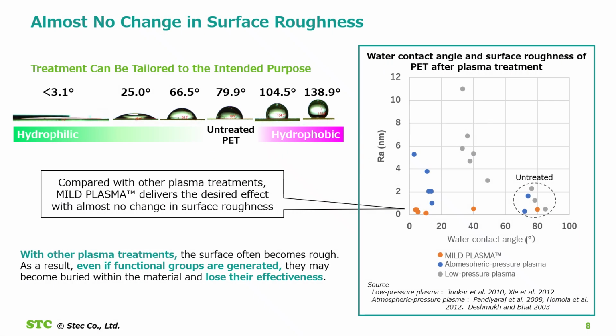Second, it causes almost no change in surface roughness. This is another major differentiator. Many conventional plasma treatments improve wettability, but they also roughen the surface. That can be a problem, especially when smoothness is critical. Take a look at the picture on the right. It shows water contact angle and surface roughness of PET after plasma treatment. It indicates that compared with other plasma treatments, mild plasma can minimize the surface roughness. In fact, with other plasma treatments, the surface often becomes rough. As a result, even if functional groups are generated, they may become buried within the material and lose their effectiveness.